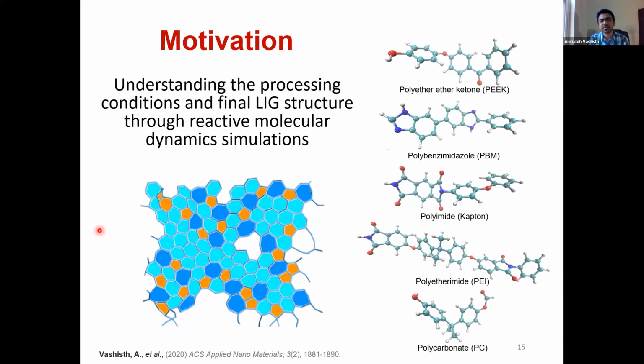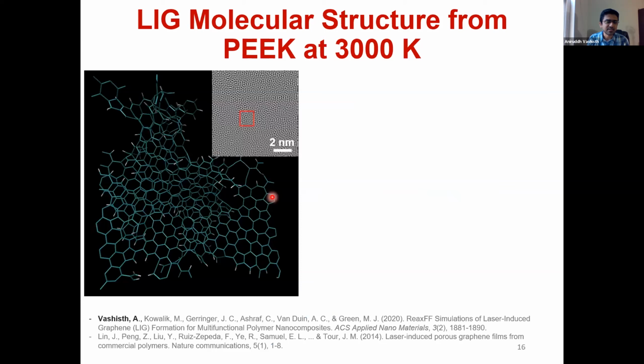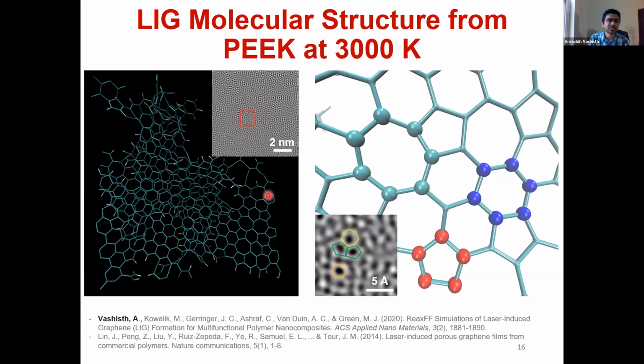It's not a planar structure because it has so many 5 and 7-member rings, but really interesting, like what exactly is happening as this molecule is getting formed. So here's an interesting comparison. You can see a virtually fabricated LIG, and you can see a high resolution TEM from one of James Tour's papers. Dr. Tour's lab actually invented this material at Rice University. So he has a really nice paper in Nature Communications where he has really high resolution TEM images. So we saw that in our simulations also. We see that 7-member rings, 6-member rings, 5-member rings are also seen in high resolution TEM images for PEEK polymer that has been converted to LIG.